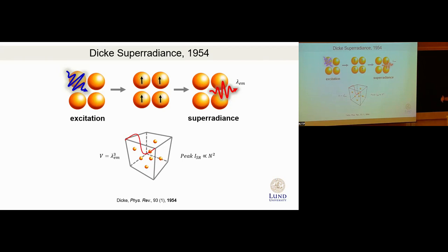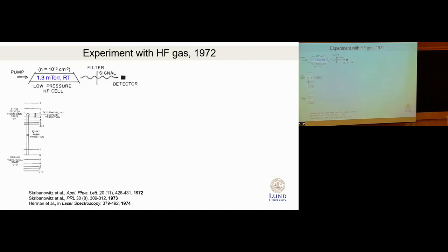Then you excite them all together, and after some time they produce this superradiant pulse with a peak intensity proportional to the square of the number of emitters. So this effect became known as superradiance. That was treated theoretically in this paper, both quantum mechanically and semi-classically. And then the first experiment came in '72.